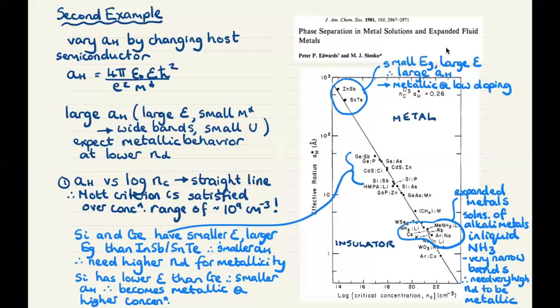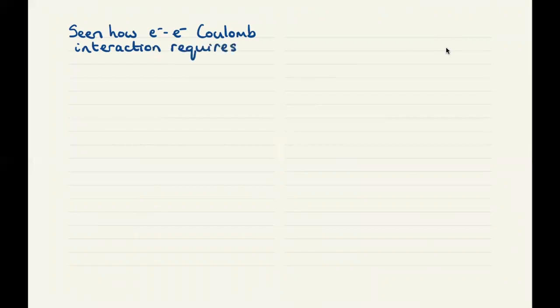Okay, so we see in both our examples here, whether we vary the hydrogenic radius and vary the U, or whether we vary the spacing between the dopant atoms and vary the bandwidth, the Mott criterion for the transition between a metal and an insulator is satisfied in both cases. Okay, so we've seen a really very striking example of how the electron-electron Coulomb interaction really requires an extension to the simple band theory picture.